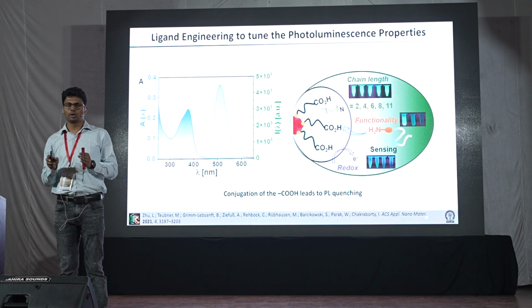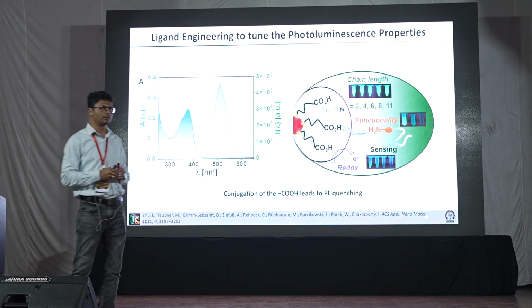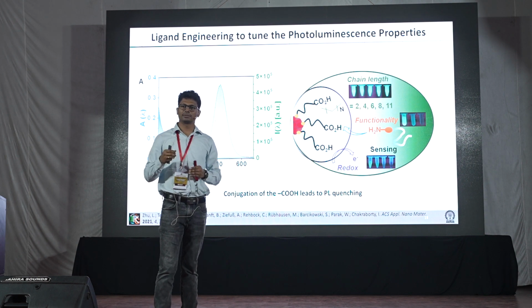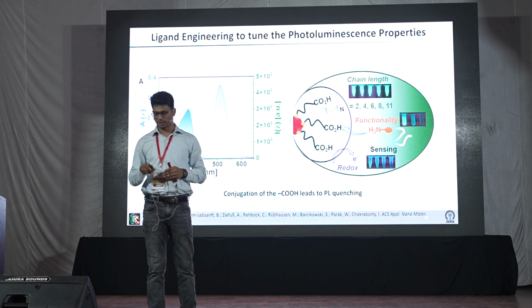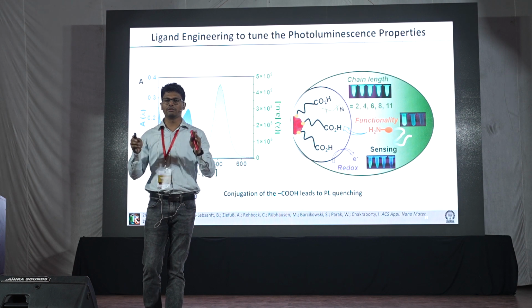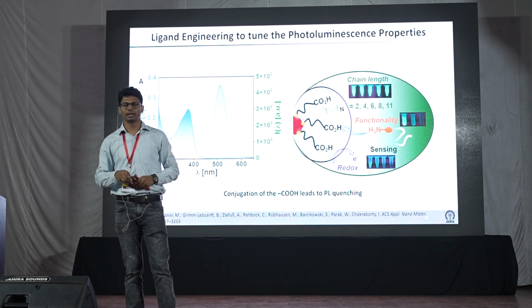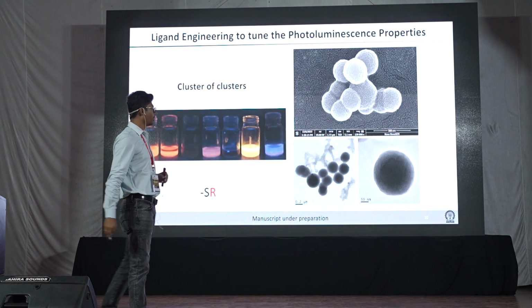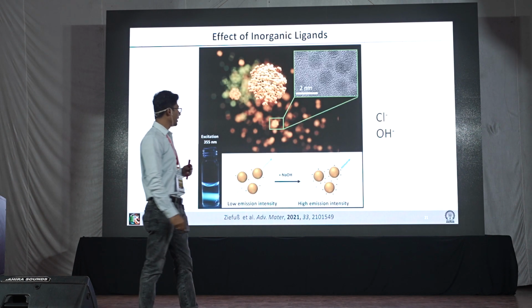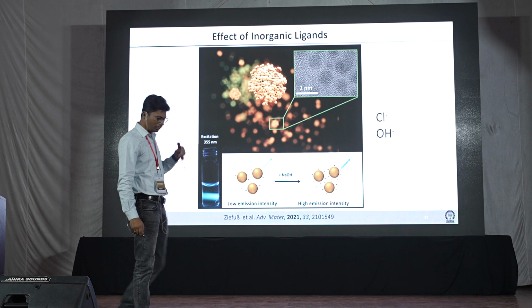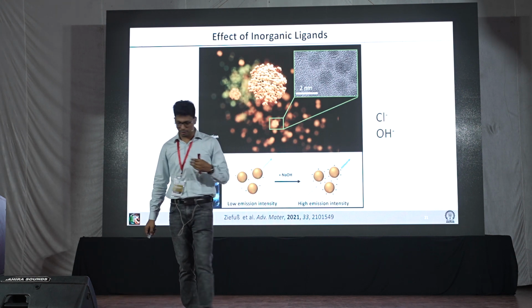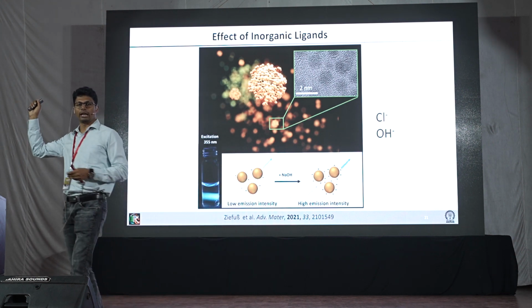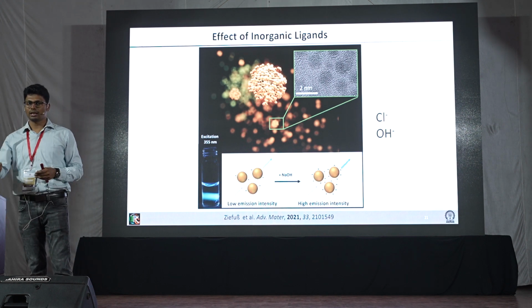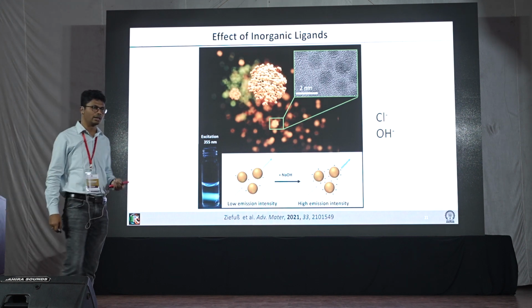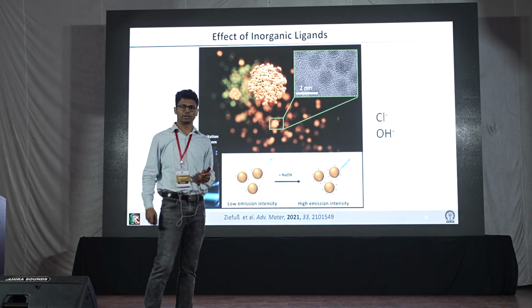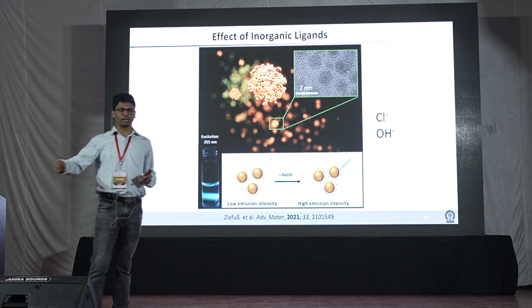Although what we can clearly say from these results is that ligands play an important role in promoting the photoluminescence quantum yield. But is it the original reason for the appearance of fluorescence? That was one of the controversial questions which many people try to understand. But what we try to point out here is that even without any organic ligand, a cluster can also be luminescent. But there are inorganic ligands. For example, this was a cluster synthesized by the laser ablation method. It's a top-down approach rather than a bottom-up approach.